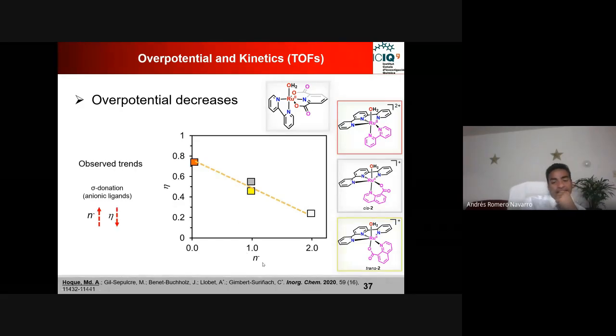So what it is saying is that if you have more sigma donating anionic ligands, you will be able to reduce the overpotential of the system. So that is very good. But the problem comes. We checked that the turnover frequency is very, very low. So it is almost useless, right? We managed to reduce the overpotential, but we are sacrificing something else. So we thought that we want to have a catalyst with high turnover frequency. So can we do that? We thought, okay, let's try.